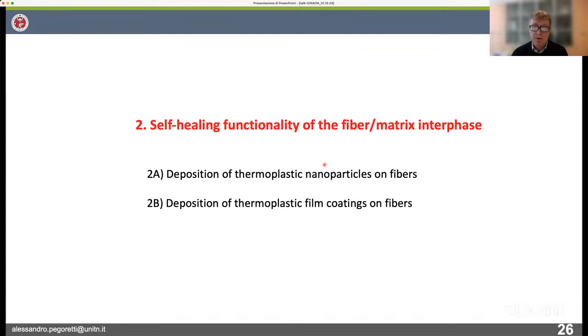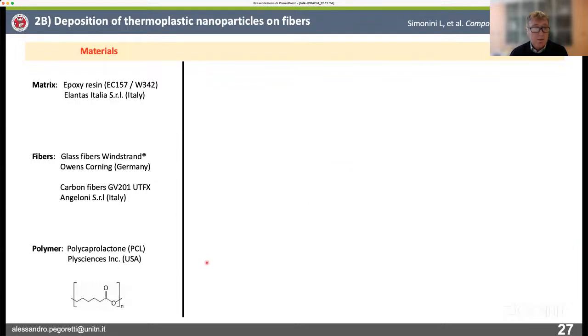Of course, the thermoplastic polymer must be properly selected. One of the main thermoplastic polymers used in this field is polycaprolactone, PCL. It has been widely studied. For example, in Lausanne, EPFL, Professor Michaud also has a spin-off company which is producing prepreg containing polycaprolactone, which is very active and can induce a repair of the polymer in the composite material. So we selected this polymer, which has a relatively low melting point, around 60 degrees, and therefore it is suitable to be used also with standard epoxy matrix.